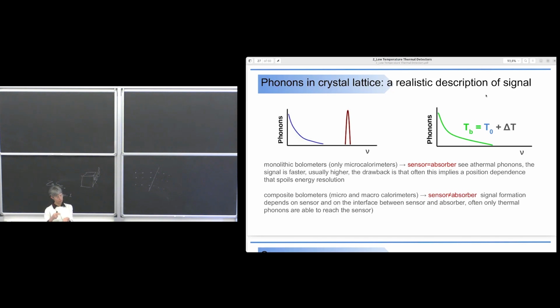And to say the truth, we have a further interface inside the thermistor, because the kind of thermistor that we use has this behavior that is described as a thermal decoupling between the phonons and the electrons inside the semiconductor. So it's a very complicated thermal model. And all these interfaces for sure help the process of thermalization of phonons. So we think that in our case, we really read out thermal phonons.